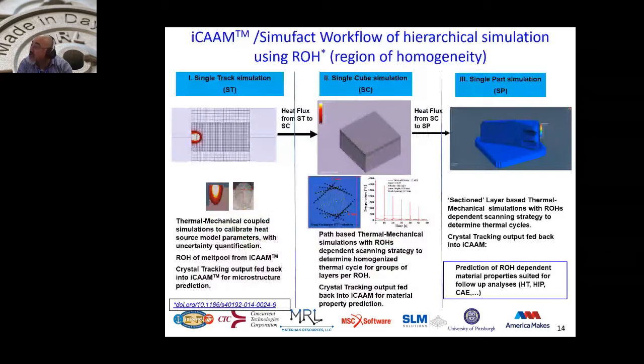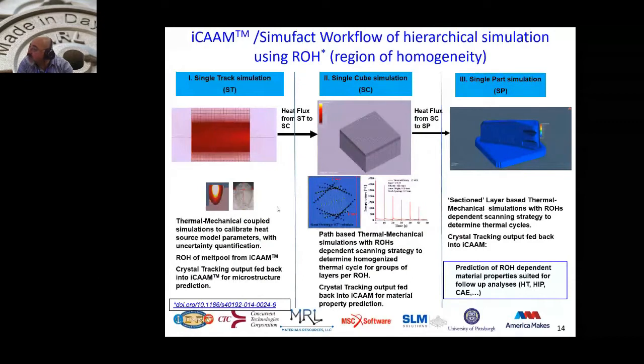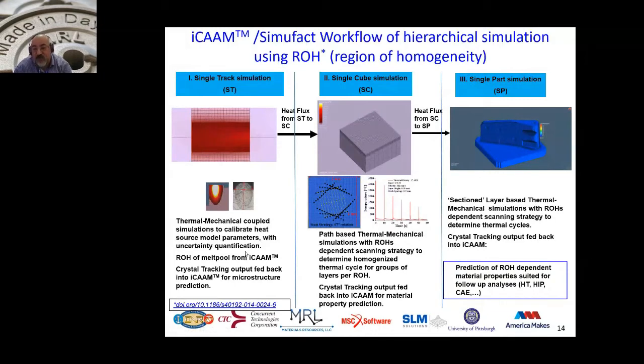And the hierarchical simulation that you're seeing on the screen right now, on the far left, we are capturing the material behavior at the single track level, where we're taking into account the morphology of the melt pool and how it is related to the morphology of the solidified melt pool. And we utilize a unique trick that we developed at MRL. SimuFact was one of the few FEM solvers that implemented what we call crystal tracking. So instead of handling the whole FEM mesh, we are able to sample it, and some of this information is in the paper that is referenced at the bottom.